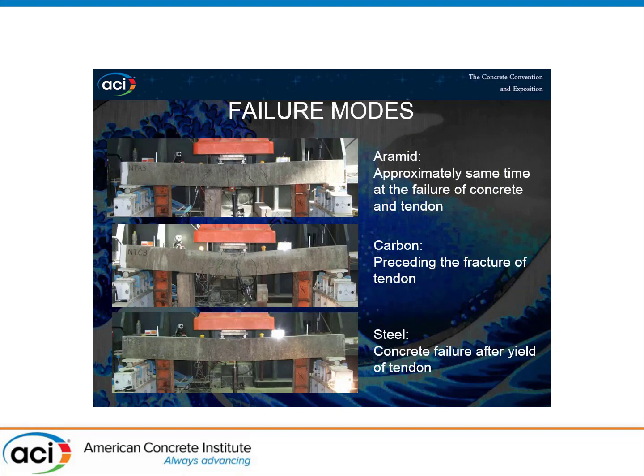Now I speak about the results of this study. This figure shows the flexural modes of the specimen. In case of aramid, approximately the same time of the failure of the concrete and tendon. In case of carbon, concrete failure preceding the fracture of tendon. In case of steel, concrete failure after yield of tendon. These results were consistent with that of the FEM calculations by applying a fiber model using the concrete compressive strength with the age of 2 months and a tensile strength of the prestressing tendons.